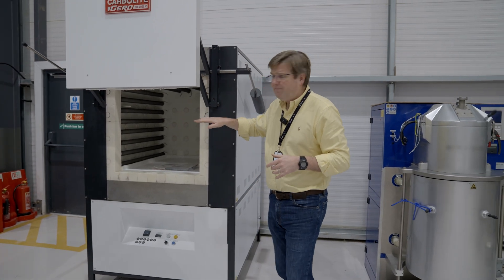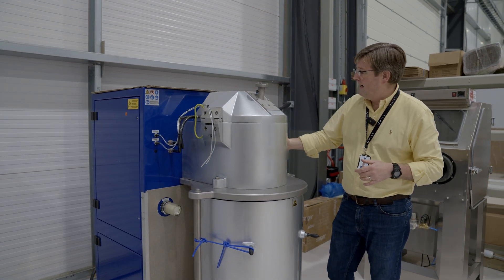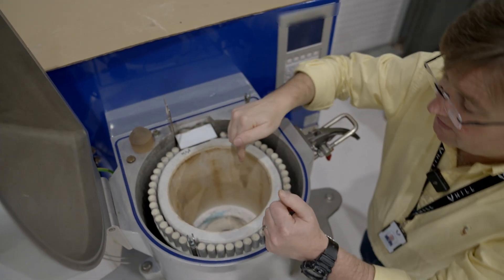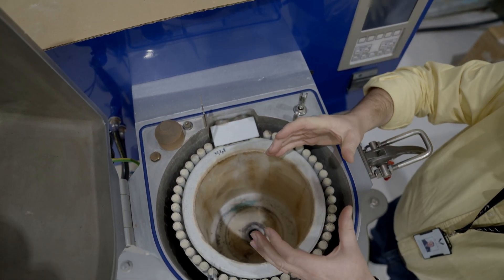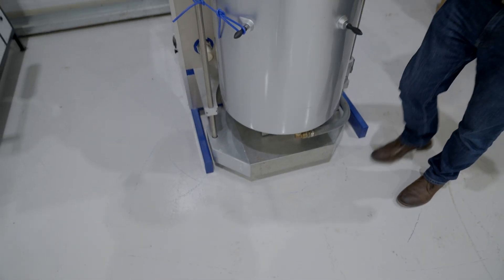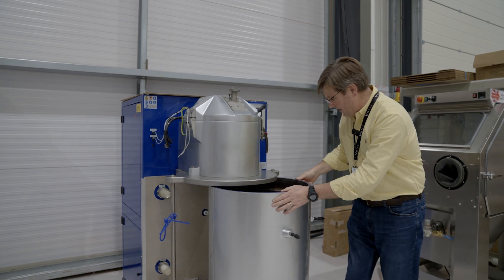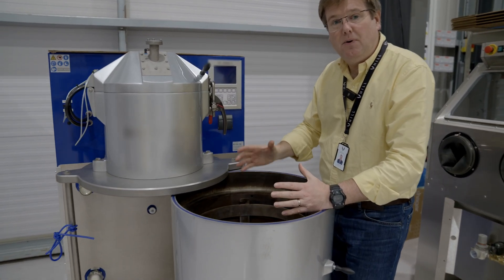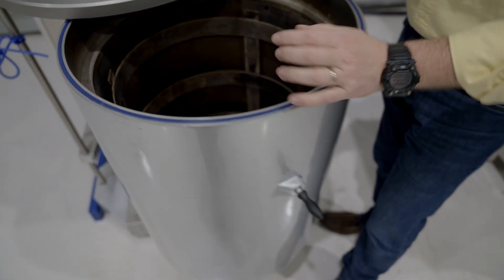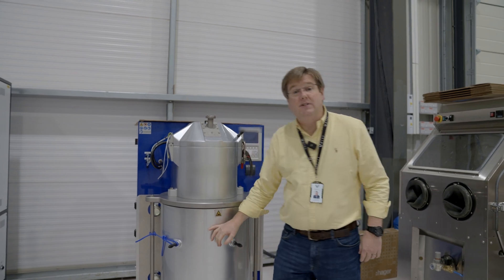We then come over to our vacuum induction furnace. At the top there is a crucible into which we put the stock superalloy material. We can melt the material and then release it through the hole at the bottom into the pouring chamber — this huge vessel at the bottom of the furnace. Our mold sits in this vessel; when it's closed and sealed, vacuum is drawn and we pour the materials down into the mold. It's a relatively simple process but requires very careful control of all the crucial parameters to make it work properly.